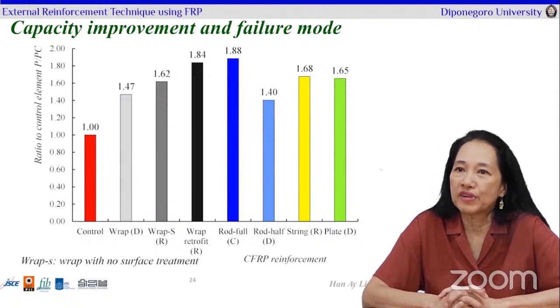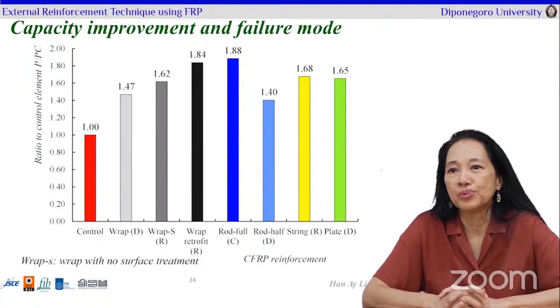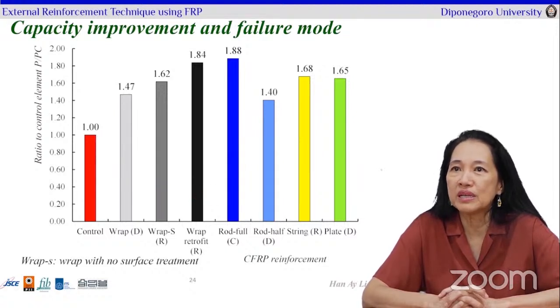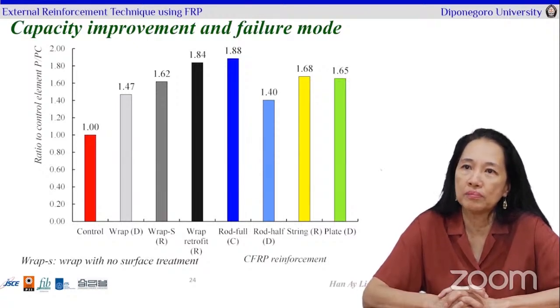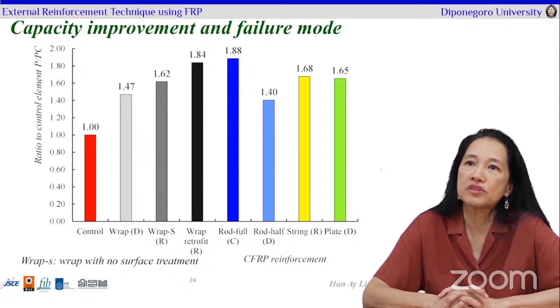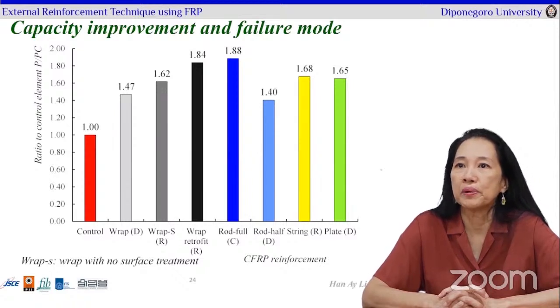If you have a cracked beam and you do retrofitting and then add the wraps as reinforcement and apply the surface treatment, then you'll have a 84% increase in moment capacity. So that means that even cracked sections do not need to be demolished anymore. We can repair them and they still will have a substantial amount of capacity in their member.